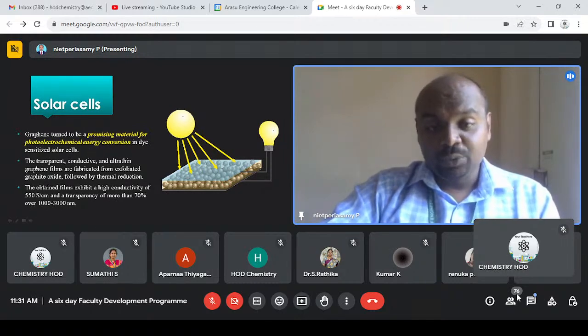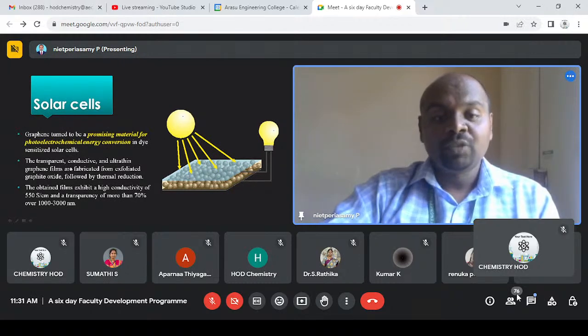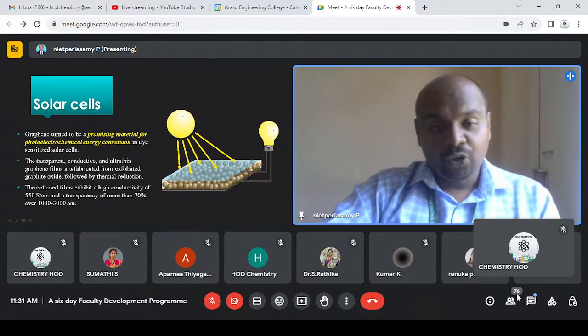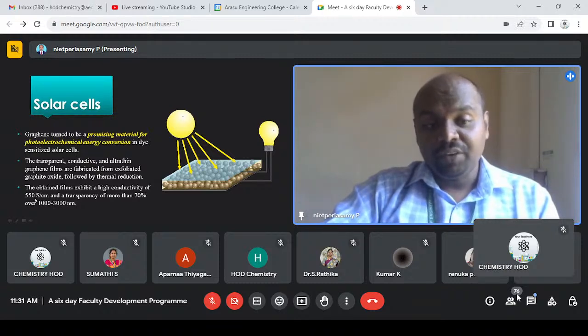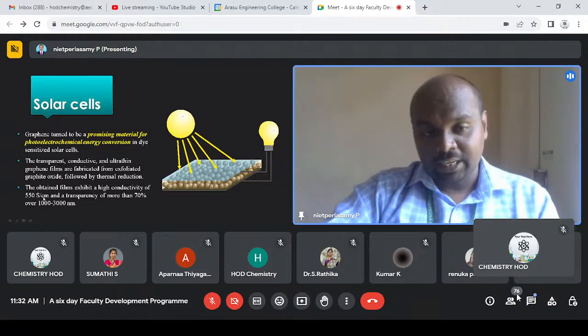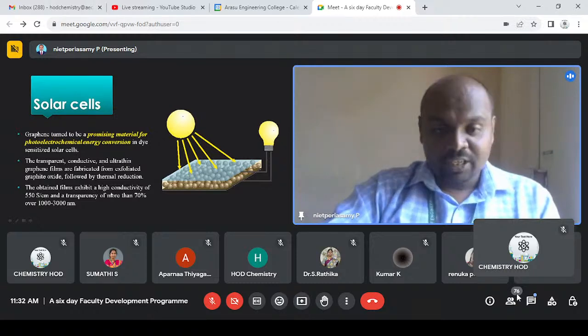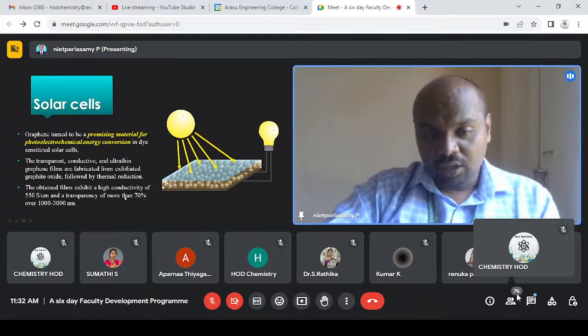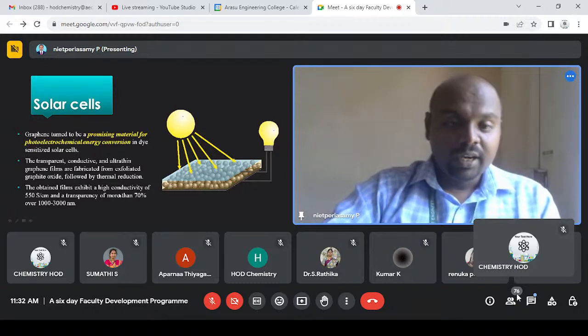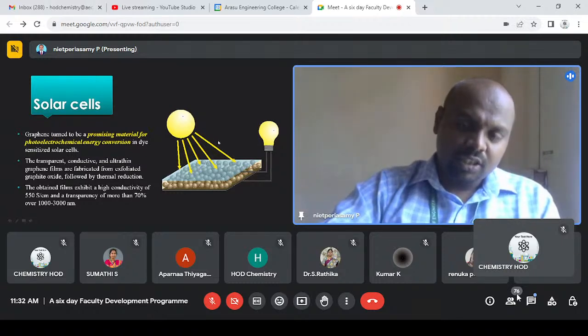The transparent, conductive, and ultra-thin graphene films are fabricated from exfoliated graphite oxide followed by thermal reduction. These are highly efficient, and the obtained film exhibits a high conductivity of 550 S/cm and a transparency of more than 70% over the 1000 to 3000 nanometer range. So nowadays solar cells seem to be transparent and also more efficient.